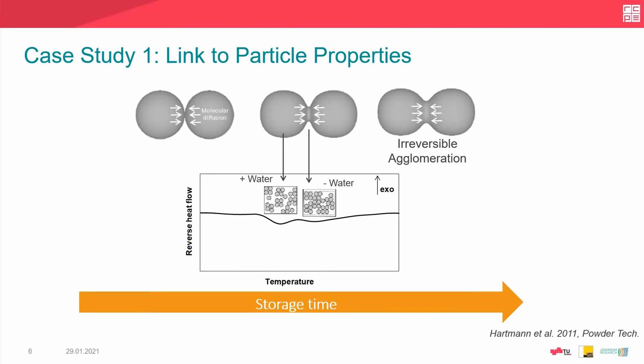In practical terms, what does this mean? We hypothesize that due to different distribution of water within the particle, we may have irreversible agglomeration developing during aging of our particles. This is detrimental because for an API that must be delivered to the lung, it has to be well dispersed. If it is irreversibly agglomerated, the particles will be too large and will not be able to reach the lung.